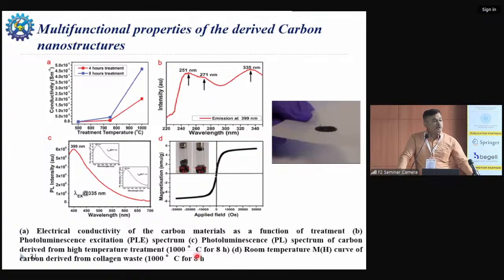And if we look at the properties, it has very good conductivity, specifically when the temperature is very high, and we got very good electrical conductivity, and it has very nice photoluminescence behavior, and it also has a magnetic behavior, which could be primarily due to certain impurities. That is what we found.